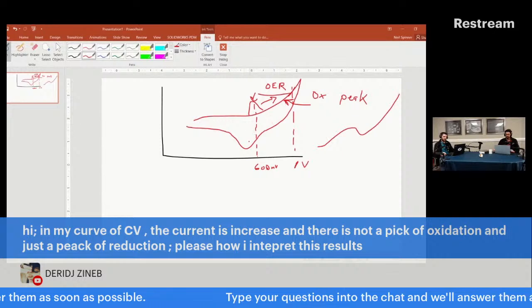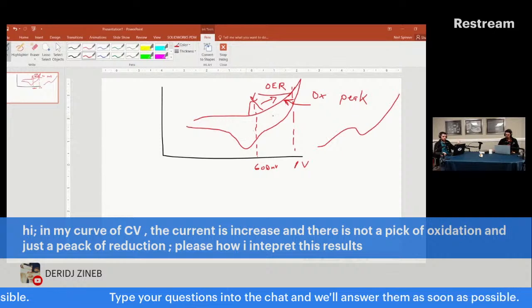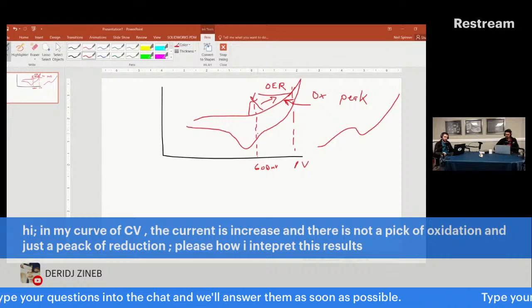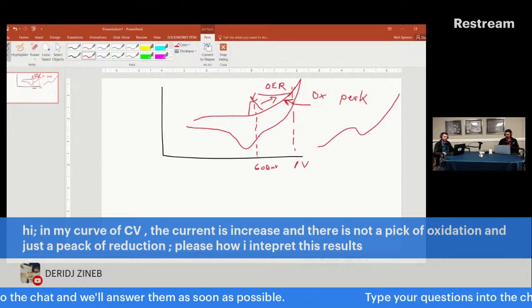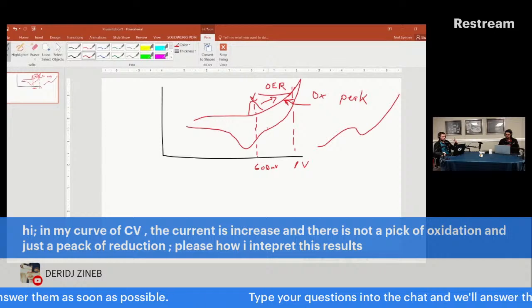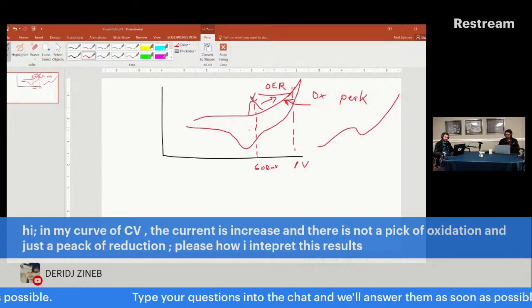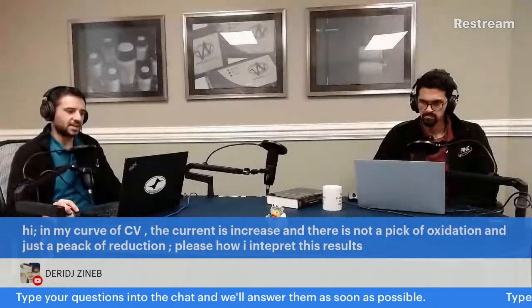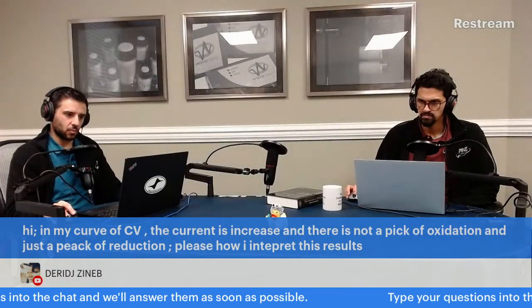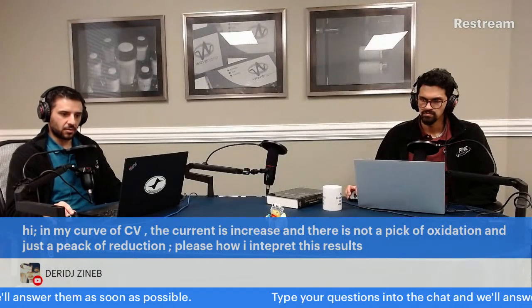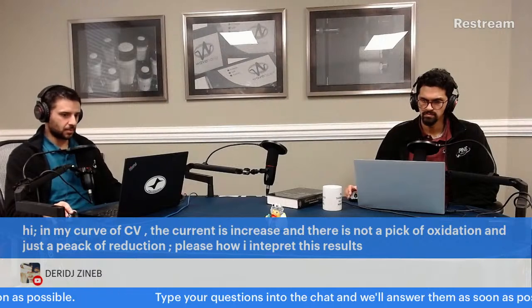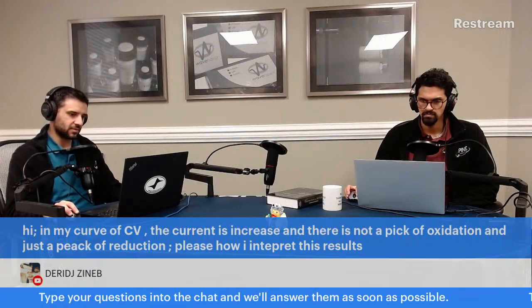And then when you scan backwards, you get the reduction peak, because you oxidized something, and so there is something to reduce. It's just at a far more positive potential than you would like to have for clarity in viewing. That's my guess as to what you're seeing and why. But again, without seeing your data and knowing specifics of your system, I probably can't answer more specifically than that, but maybe consider those things if that is accurate for what you're seeing.